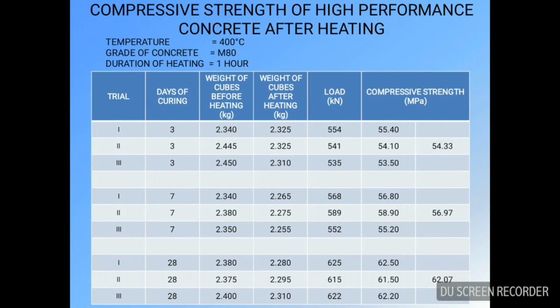Now the M80 grade of concrete was also done with the same procedure, first heating at 400 degrees Celsius for a duration of about 1 hour. The strength came around to be 54.33 after 3 days of curing, 56.97 after 7 days of curing, and 62.07 after 28 days of curing.